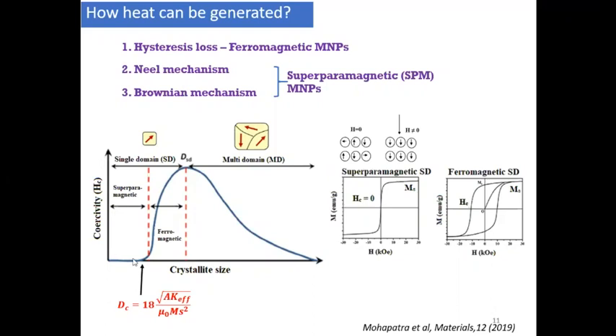If we see coercivity versus crystallite size, as we decrease the crystallite size, this is the multi-domain region, and here it comes to the single domain region, and still it possesses coercivity. Coercivity is maximum here, and in this size range it is generally used for magnetic energy storage devices. However, if you decrease the size of the particles, the coercivity decreases, and at a particular size the coercivity is zero. When the coercivity is zero, we get the superparamagnetic nature.